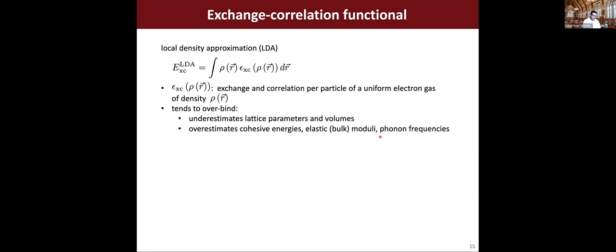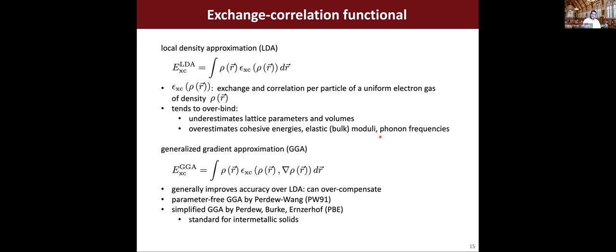just because of the nature of how the exchange correlation functional works. The next level theory is called the generalized gradient approximation, where the exchange correlation term is not just dependent on the charge density, but also the gradients of the charge density. So we're going to incorporate information on what the derivatives look like. This generally improves over LDA, but it can also overcompensate. There are two important examples in the literature. There's the parameter-free GGA developed by Perdew and Wang in 91. And then there's the simplified version, developed by Perdew, Burke, and Ernzerhof, called PBE, after their names. This is what we're going to be using in our examples,